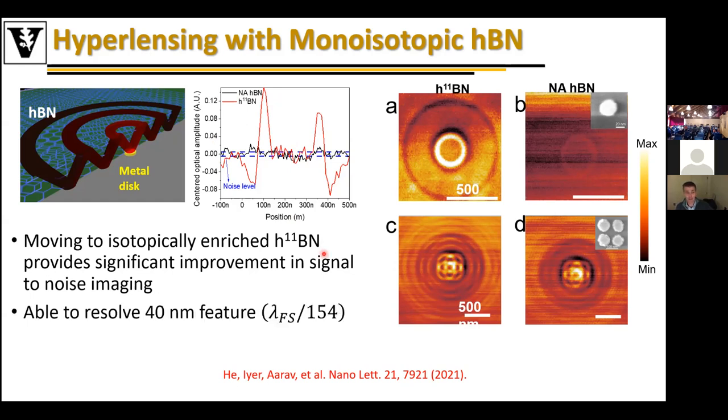we imaged here. But even just with that structure, this gives us a demonstration of being able to resolve a 40 nanometer feature, which is effectively 154 times smaller than the free space wavelength, as well as resolve separations between structures down around 25 nanometers, which is about 270 times smaller than the free space wavelength.